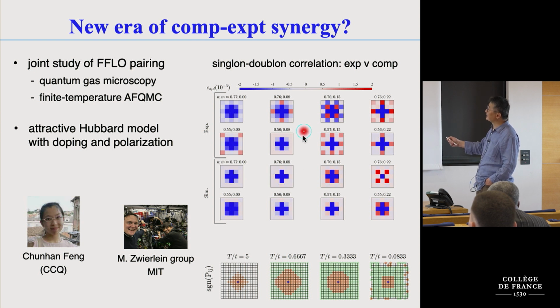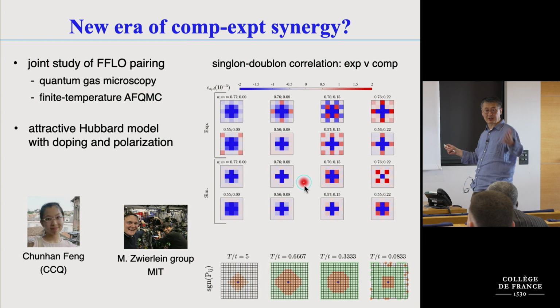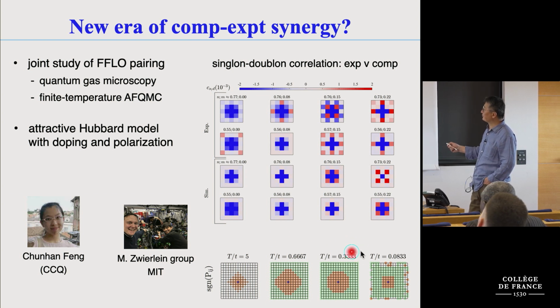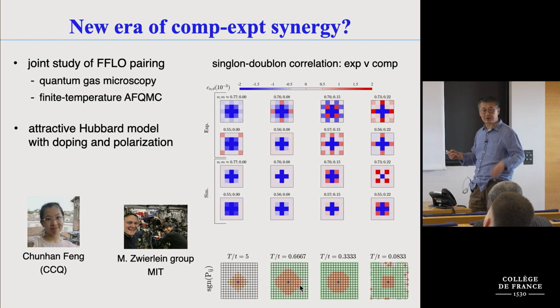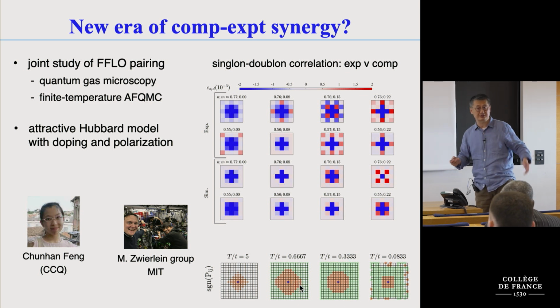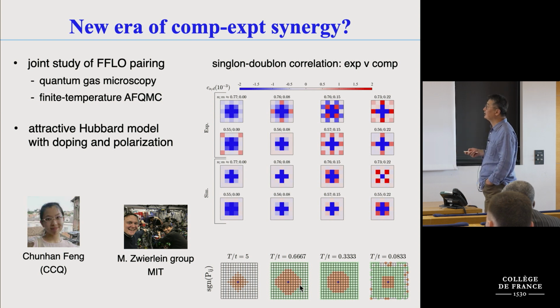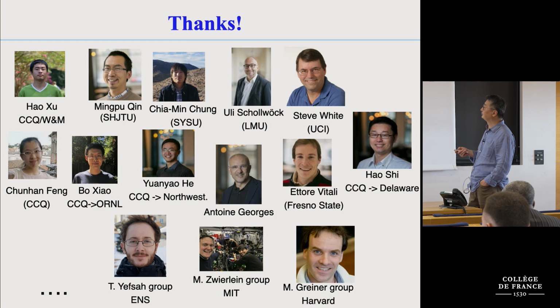So what we did, in this paper, is a careful comparison at about 0.25 of every quantity they measure, and then we use AFQMC to go down to below this temperature. And it turns out the earlier indications are the same kind of physics that eventually at low temperature lead to FFLO. So I think this is very exciting. There's opportunity to really experimentally probe.